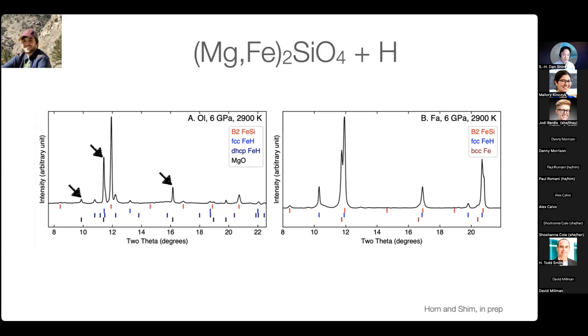After the chemical reaction of the olivine and hydrogen, we find that MgO appears in the diffraction pattern. Again, we didn't start with MgO. We started with (Mg,Fe)2SiO4. So somehow this material breaks down. Olivine breaks down and forms MgO. And we find the iron-hydrogen alloy, indicated by blue arrows, the same way that we observed for MgFeO, which means that iron 2+ is again reduced to iron metal. Now, more interestingly, in this experiment, different from the MgFeO experiment, we find iron-silicon alloy indicated by these red arrows, meaning that now silicon also undergoes reduction from Si4+ to Si metal and alloys with iron.